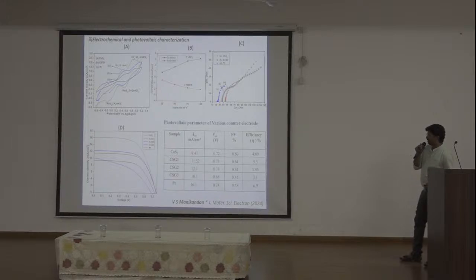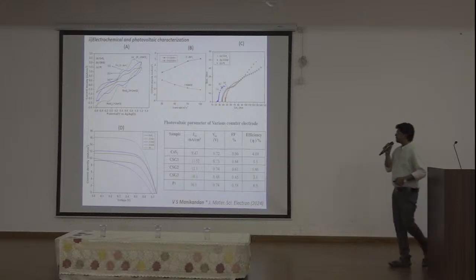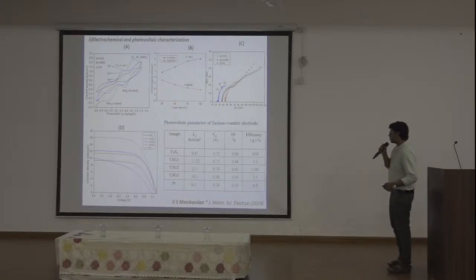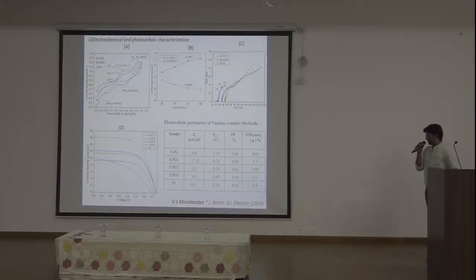So this implies that the CSG2 sample indicates the maximum power conversion efficiency of 5.46. After inclusion of RGO, there is also a negative impact on the fill factor. We can see here the CSG3 sample is decreasing the fill factor due to the higher charge transport resistance.